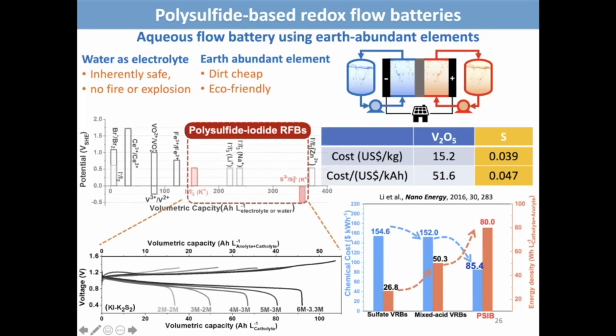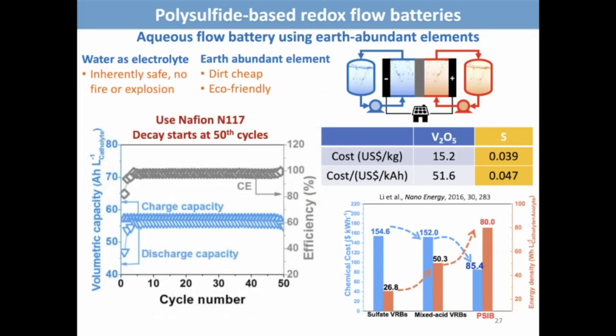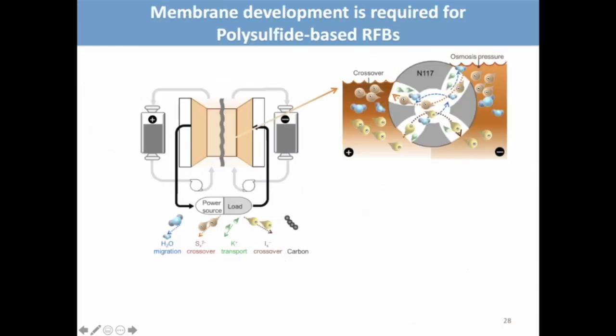In the market, there are polysulfide bromide flow batteries, but bromide could be a toxic gas during cycling. So in 2016, we demonstrated using iodide as a couple with polysulfide. This system in fact achieved a lower chemical cost compared to the vanadium flow battery and promised higher energy density. When we did this in 2016, unfortunately, we were using a commercial Nafion membrane and we always observed decay starting at about 50 cycles. And this decay is directly related to a few reasons.